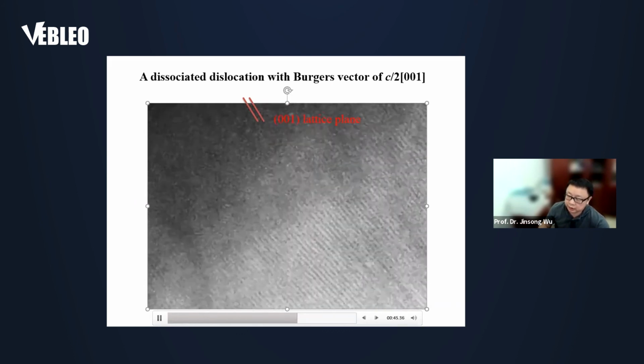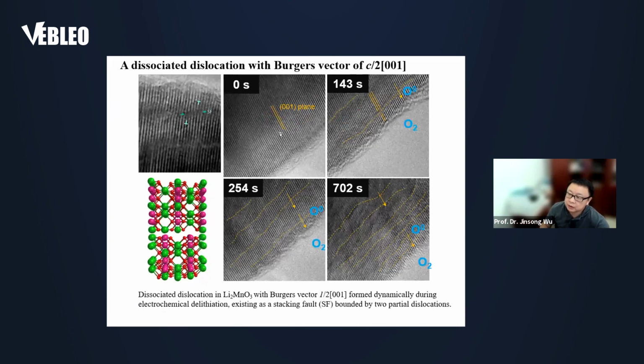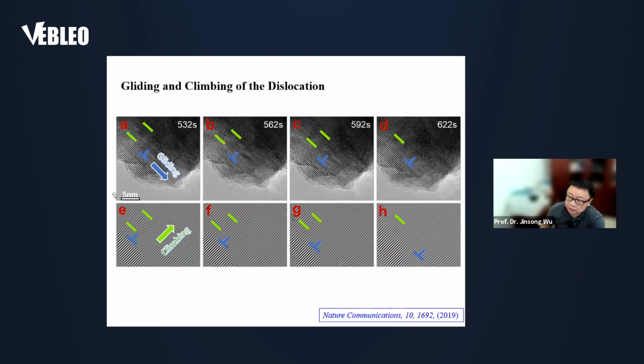And if we take out the snapshots from the previous video, what we can find is that the density of the defects becomes larger and larger. At the same time, by looking carefully at the enlarged image of these defects, they can be identified as dissociated dislocations, and the Burgers vector is half of 001. And here's a structure model of this dislocation. And then, when we did more experiments, what we can find is this dislocation can not only glide but also climb, meaning that during the delithiation, the mobility of this dislocation is quite high.